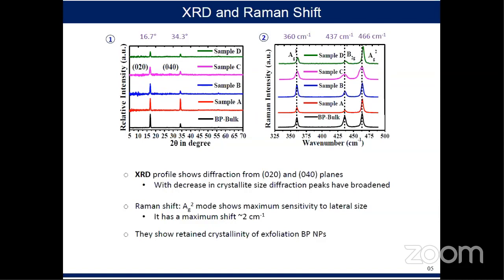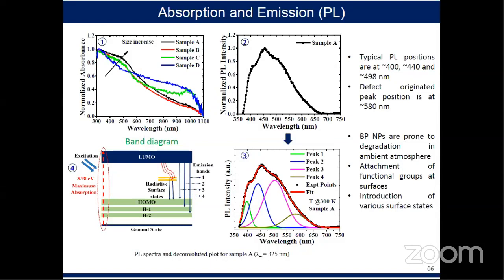So next slide. We then characterized using optical spectroscopy like absorption and photoluminescence spectroscopy. In absorption spectroscopy in figure 1, we can clearly see broad absorption from all the samples, but their main peak is around 400 to 500 nanometers. As the nanocrystal size goes down from sample A to D, we found a blue shift, which is in accordance with quantum confinement effects.